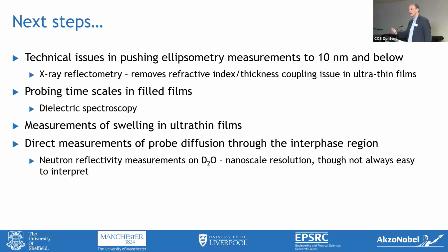We can measure surface-specific ordering using grazing incidence X-ray diffraction. That works for a free surface. It's slightly more tricky to do it for the buried interface, but those are things that can give us a handle on that. I have to say, I would be quite surprised, well, maybe not, I don't know, but I think I'd be surprised if it was a really important factor in epoxy systems and these cross-linking systems. But it is something that happens. It is another dimension to the interface.